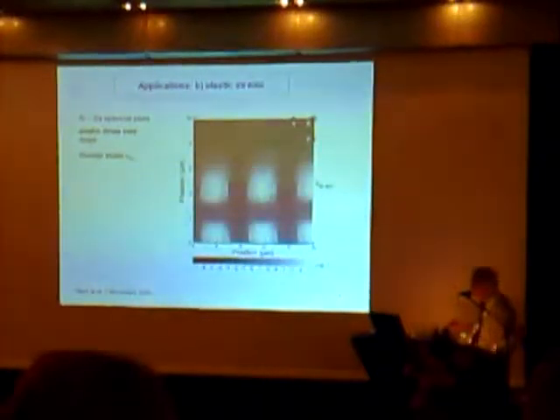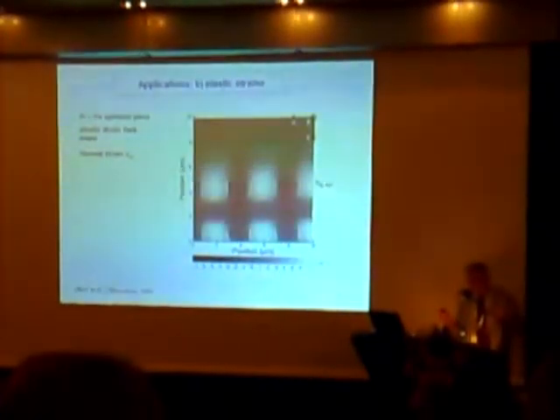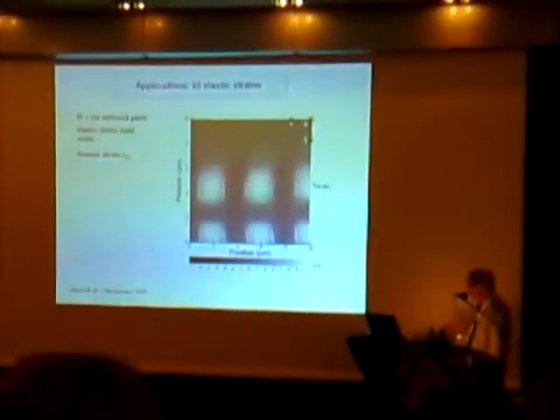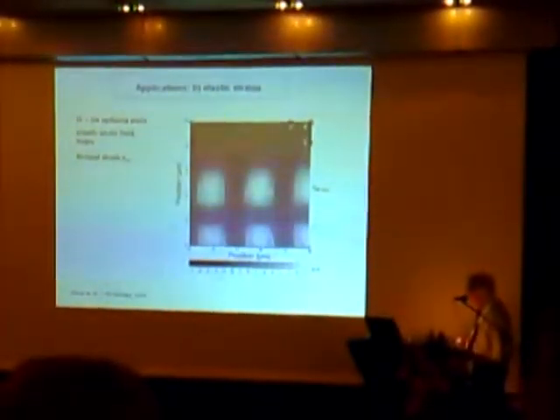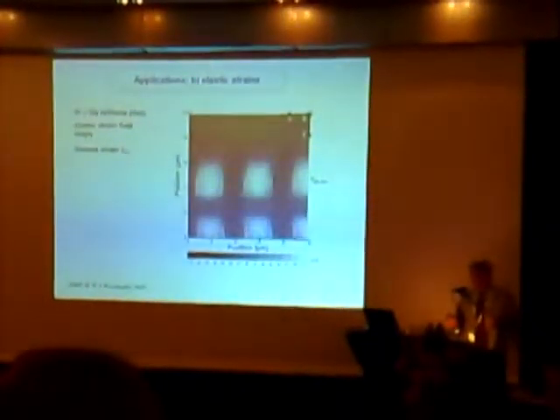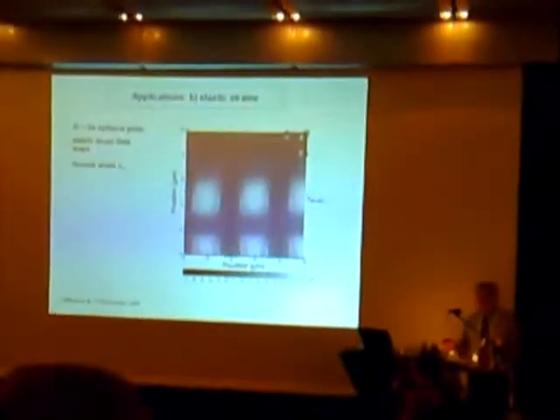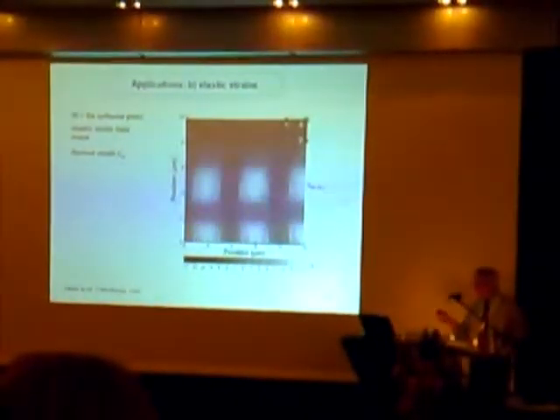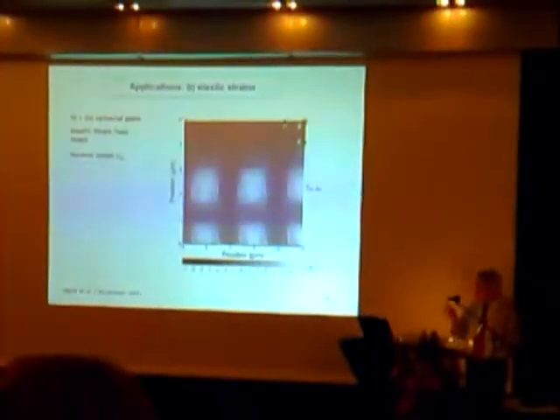As I think these are areas where germanium is deposited on silicon, so it increases the strain by lattice distortion. And these are the elastic strain values as measured on this map. And they fit very well with what you can calculate. In fact, it fits so well that now you can estimate the composition from the elastic strain. Since you know that so much germanium will give you so much elastic strain, if you know the elastic strain, you can say, well, I've got so much germanium. So this gives you, if you like, almost chemical composition.